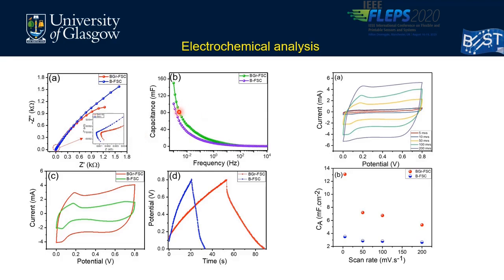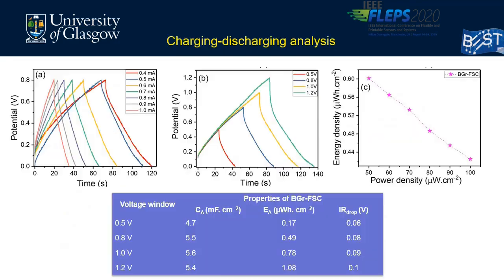The capacitance value shows a double-time enhancement after graphite coating. This is even visible from the CV as well as GCD analysis. The variation of the CV curve with different scan rates also shows more of an EDLC-type double layer formation, with a small redox peak around 0.1 volt, which arises from the redox reaction taking place in the silver metal. The variation of the areal capacitance with the scan rate also shows that the graphite coated devices have almost double the capacitance compared with the non-graphite coated fabric.